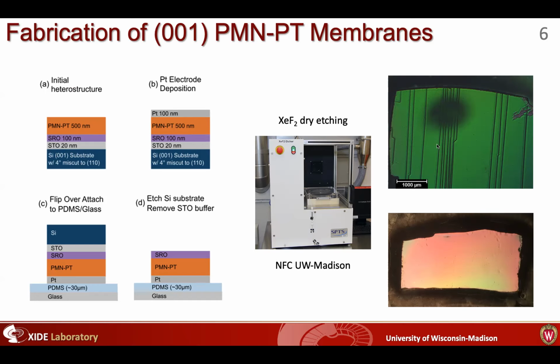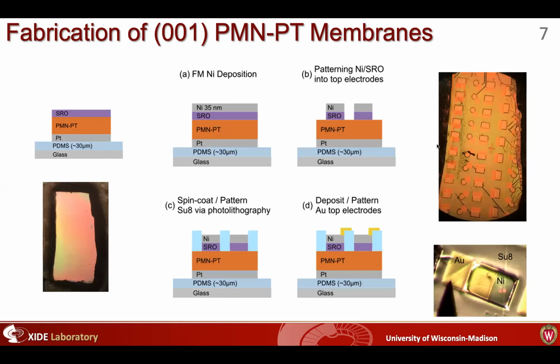These membranes are not perfectly stable. They're highly sensitive, but occasionally you can even get some that were completely crack-free, mostly under pretty lucky conditions. And as I'll show on the next slide, I then take these freestanding films, deposit my ferromagnetic nickel, and then I also add an SU8 and gold kind of offset electrode protection layer. And through later fabrication, you do see kind of more cracks arising.